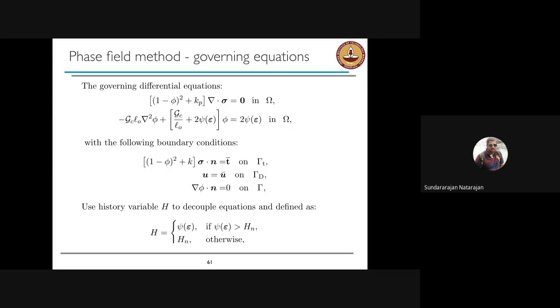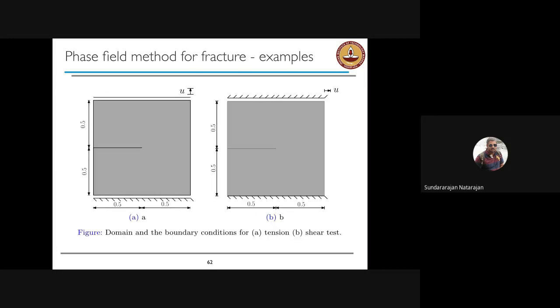So we just use the conventional finite element method to solve these two equations. We can write the weak form for it, and then we can use traditional elements to do it. And the point to note here is that the crack is not represented explicitly, but implicitly using the phase field variable. So I'm going to show you two examples: a classical example where you have a square block with a crack of length 0.5 under tension, and another example where the same square block with a crack is subjected to shear.